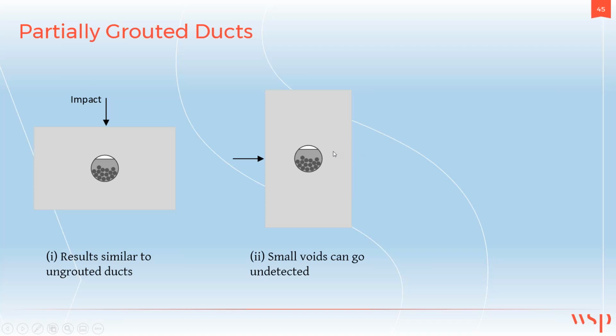Whereas for the second configuration, a small void may not even be detected at all. So the results may appear as if this is a fully grouted duct. So looking at these two scenarios, we see that we may have the exact same size void, but we'll get completely different results because of where the void is located with respect to the impact surface.